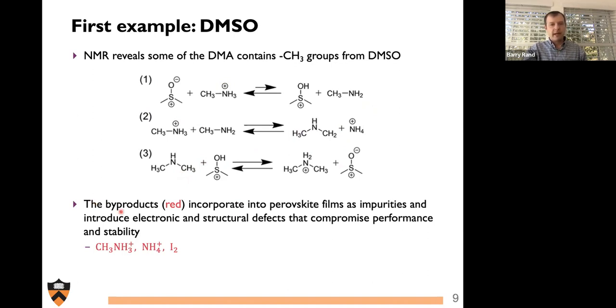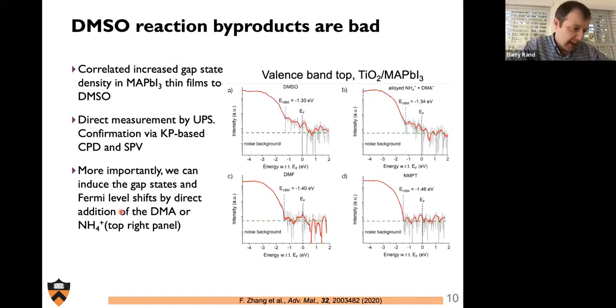And in the context of our SETO award, what we did was we incorporated these additives either through the reaction of DMSO and methylammonium being together in the same ink, or by the action of specifically alloying and introducing ammonium and dimethylammonium into an ink that was devoid of any DMSO. So we wanted to either put those byproducts in as a result of reaction or put them in overtly.